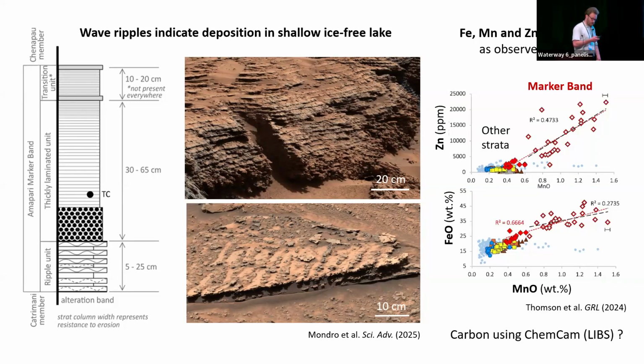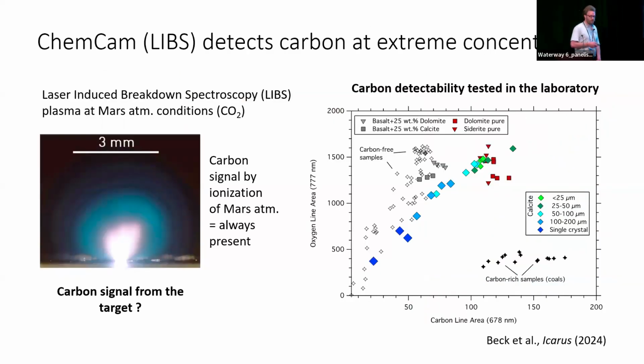What we wanted to try on this study is look also at ChemCam data, because ChemCam is sensitive to light elements like carbon, and see if we could find it. A warning is that carbon is really hard to detect with ChemCam laser-induced breakdown spectroscopy on Mars in particular, because when we produce the plasma from the laser, it forms a plume in the atmosphere which excites the atmosphere itself. The atmosphere is CO2, so there is carbon coming from the atmosphere that is acting as noise. So understanding if the carbon comes from the target or the atmosphere is really tricky.